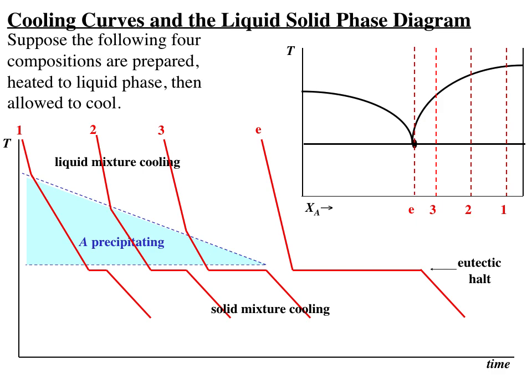Now let's look at the curves. Let's look at the appearance of what a curve would look like with temperature versus time as I cool these samples. Look at the E curve to the far right. I have a diminishing temperature with time. It looks like a nice linear function of temperature with time until suddenly I come to not an inflection, but actually a discontinuity in the curve. It bends over to the right. And notice at that point, I have no decrease in temperature for a long period of time.